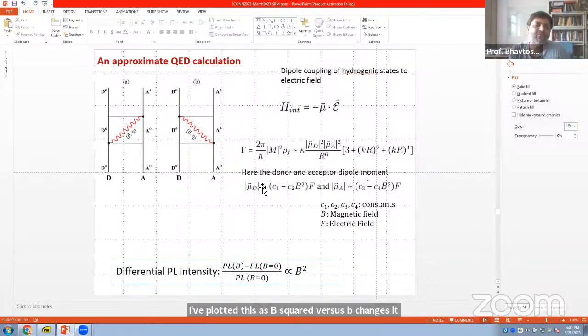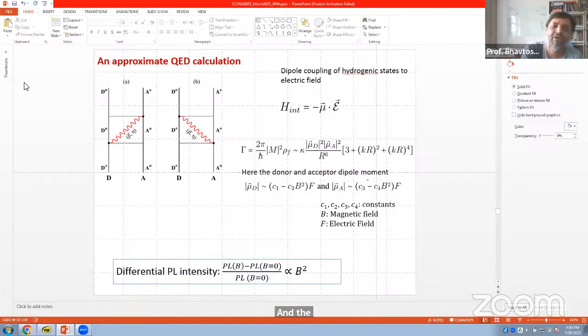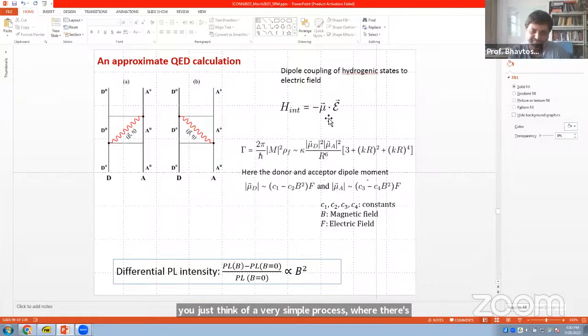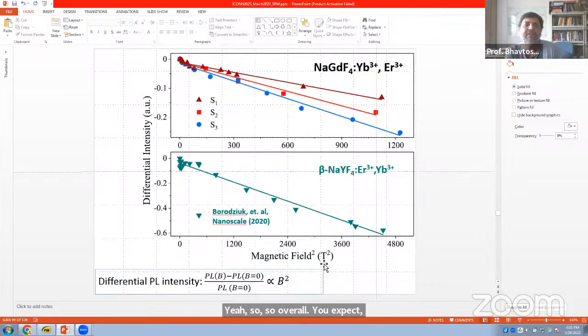And then one can do a simple calculation, thinking of FRET as some kind of photon exchange between the donor and the acceptor atoms or ions. If you think of a very simple process where there's a dipole interaction, then one can show that indeed it would be a 1 upon r to the power 6 dependence in the leading order, and also that you will have a B² dependence. So the efficiency of this FRET process would depend on the dipole moments of the donor atom and the acceptor atoms, and those dipole moments themselves get affected as B² of the applied field. So overall you expect a B² dependence, and that's what one has observed.